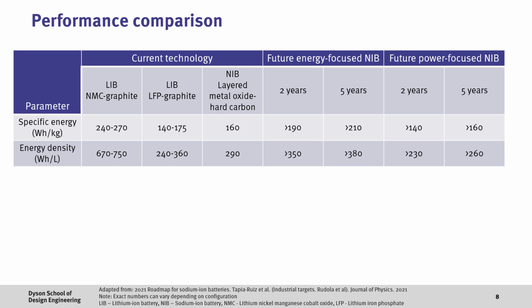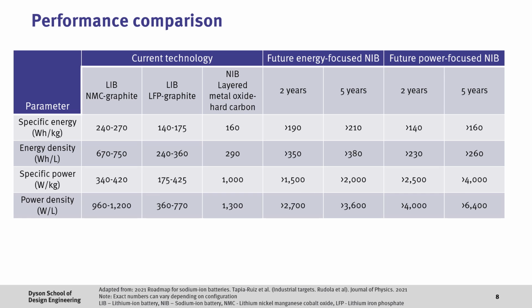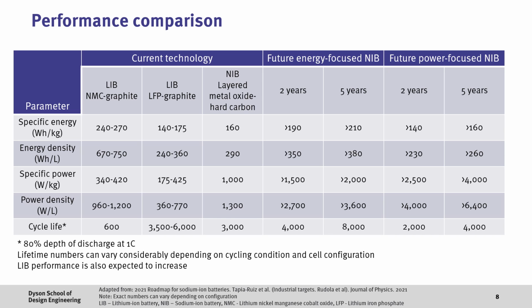However, when we look at the volumetric energy density, we can see that improvements are still needed, in part due to the low density of hard carbon compared to graphite. This is not too far away from lithium iron phosphate, however quite far away from NMC lithium-ion cells. For gravimetric and volumetric power density, you can see that sodium-ion has some clear advantages due to the high sodium-ion mobility in the electrodes. And for lifetime, there are some clear advantages also. However, this depends heavily on many factors and this table should not be taken as universal.